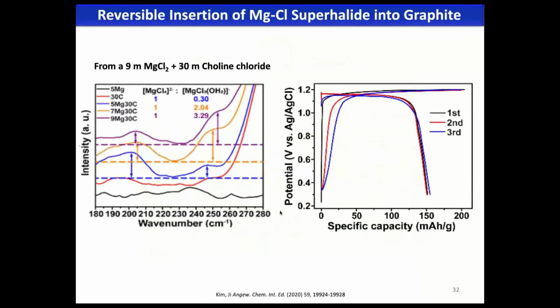And we studied different systems. This is one example. We studied graphite, and if you oxidize graphite in electrolyte, the electrolyte normally will decompose. That happens to organic electrolyte. If you use aqueous electrolyte, water will evolve into oxygen. In this case, we studied a concentrated electrolyte, you can call it deep eutectic solvent, or water-in-salt electrolyte, which is quite popular, recently introduced by Dr. Xu and Dr. Wang. So we did lithium systems, and we moved to zinc systems, and eventually here we have magnesium systems.